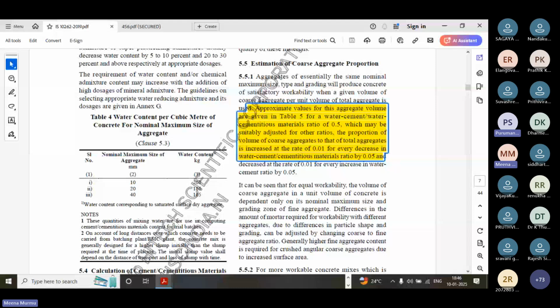Here, in Table 5, approximate values of the aggregate volume are given for a water-cement or cementitious material ratio of 0.5, which may be suitably adjusted for other ratios. Suppose we have taken 0.42. For every decrease in the water-cement ratio of 0.05, the proportion of the volume of coarse aggregate to total aggregate is increased at the rate of 0.01, and decreased at the rate of 0.01 for every increase in water-cement ratio.